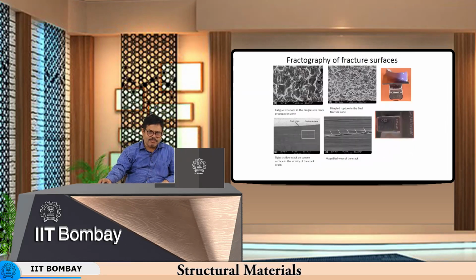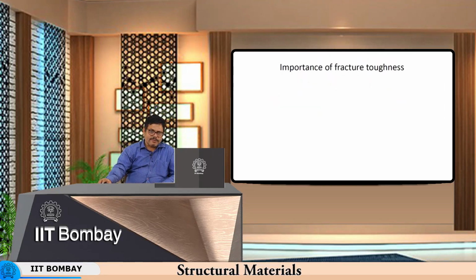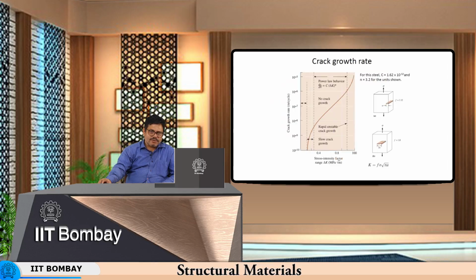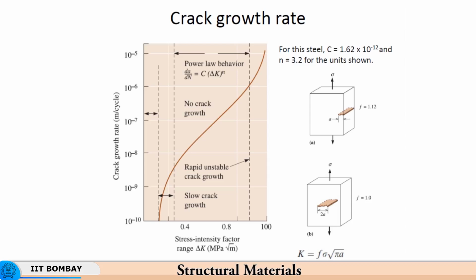So, that is what we will be able to see now in this case. The crack growth rate is given by dA by dN, where A is the length of the crack and N is the number of cycles to fatigue. Here you see that the rate of change of crack is not equal everywhere. It is not the same everywhere. You could have a surface crack, which means a surface defect, or you can have an internal defect.